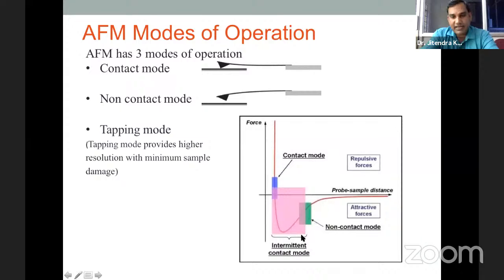That's why this bottom one can come as an attractive zone, and then again it can move to high forces, and because of that it again goes to 0. So initially your repulsive forces are there, but after some time it is attractive forces because of the high force applied over the tip and sample. The atomic bonds, the weak van der Waals forces, atomic forces attract this tip, and it can adhere to the surface. Because of that, this zone will form in contact mode.